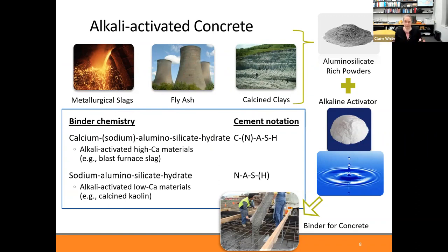So we need to activate the clay to get it to dissolve, and then for a mechanically strong binder phase to form, to give concrete strength. And so we use an alkaline activation process, for example, sodium silicate, a high pH system. And this is alkali-activated concrete down here that's actually been made with a combination of blast furnace slag and also fly ash. It behaves at the macroscopic level in a very similar fashion to Portland cement concrete, but the fundamental phases within this material are different.